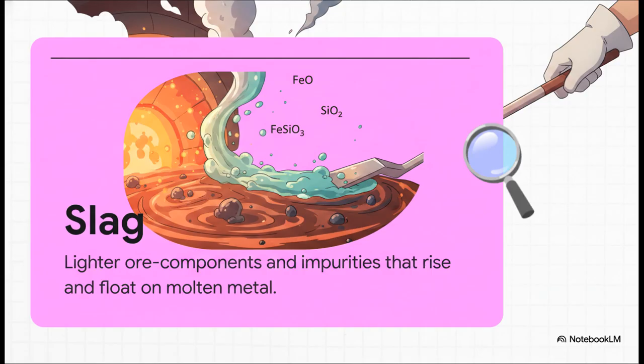Iron, which is still stubbornly mixed in with our copper, actually has a much higher affinity for oxygen than the copper does. Because of this, it forms iron oxide first. This iron oxide then reacts with the silica we've added to create what metallurgists call slag, specifically iron silicate. Think of slag as a lighter layer of liquid impurities that separates from the denser metal. Picture a pool of molten, glowing liquid rock just floating right on top of the heavier liquid copper beneath it. It is a superheated, dangerous layer that foundry workers have to carefully skim away.